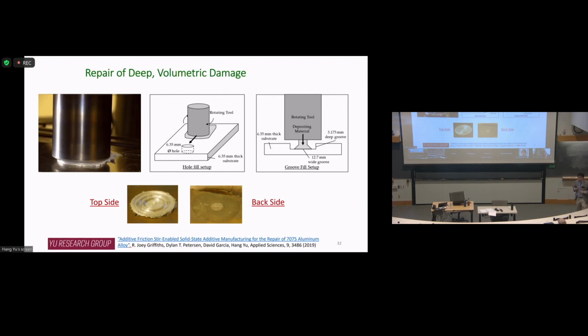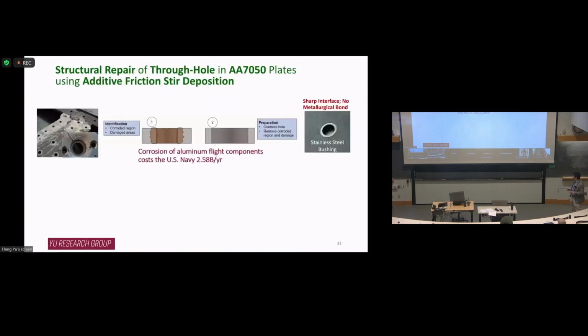We showed that to some Navy people in 2019, and they said, we actually have a project for you to think about. Turns out the Navy suffers from a long-term corroded hole problem. The big airframes have a lot of holes for fasteners, and during service you get corrosion all the time. The corroded material surrounds the hole, and you have to remove it, so your hole becomes bigger and the fastener won't fit. How do you address this? The current strategy is to fabricate a bushing structure, like a ring, and mechanically insert it. The airframe is made of aluminum 7050, and the ring is stainless steel. Making the ring is time-consuming and expensive. Also, you don't have bonding between them. It's just mechanical interlocking, and you have a sharp interface.